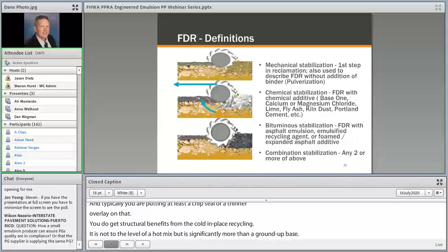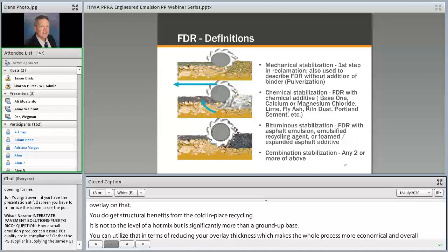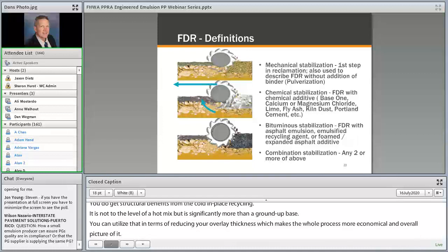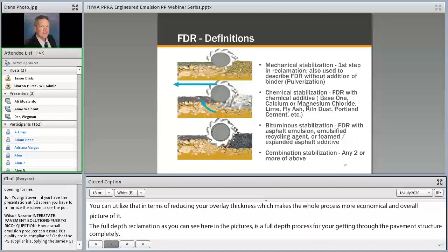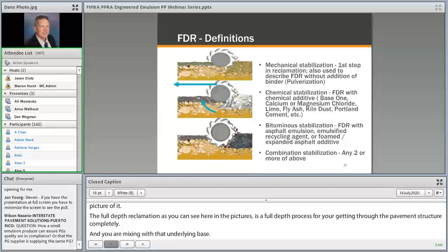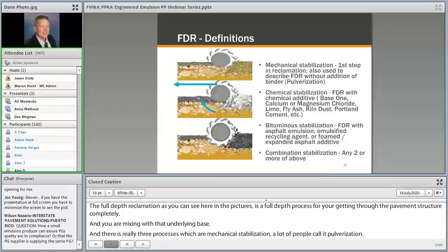And then the full depth reclamation, as you can see here in the pictures, it is a full depth process where you're actually getting through the pavement structure completely, and you're mixing with that underlying base. And there's really three processes, which are mechanical stabilization. A lot of people call that pulverization, and that is just basically going in and grinding up the pavement, combining it with the base material, and creating a new unbound base through that process.